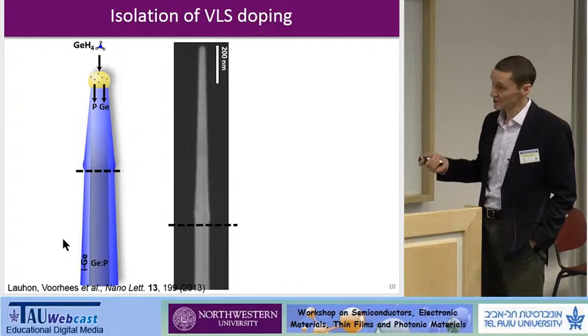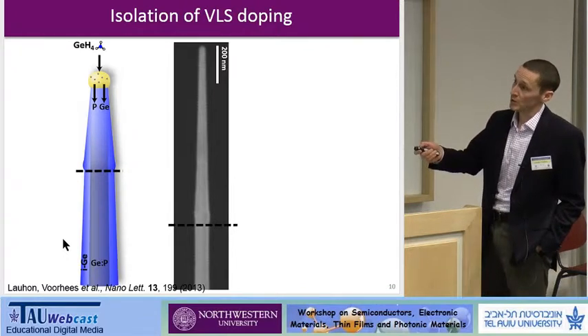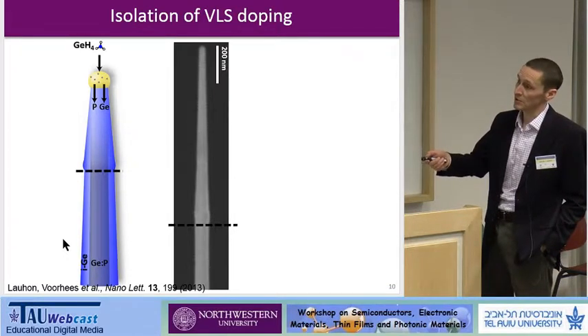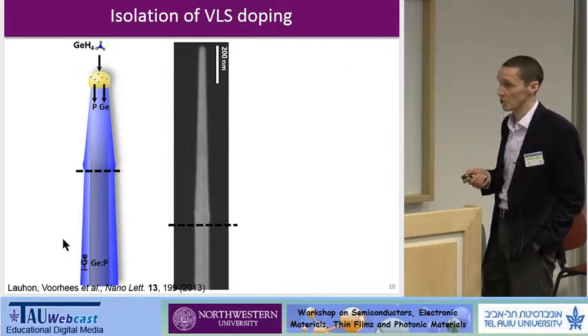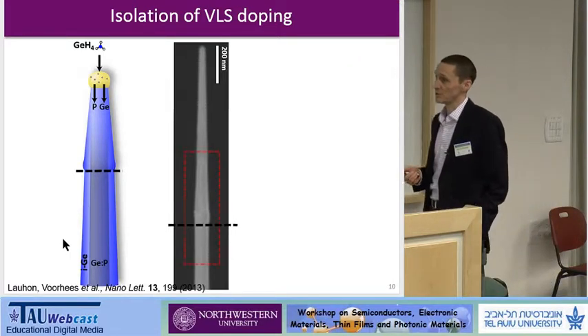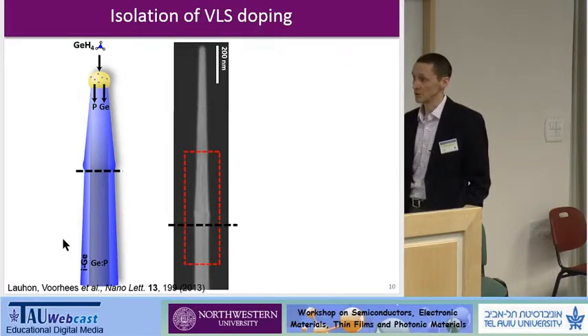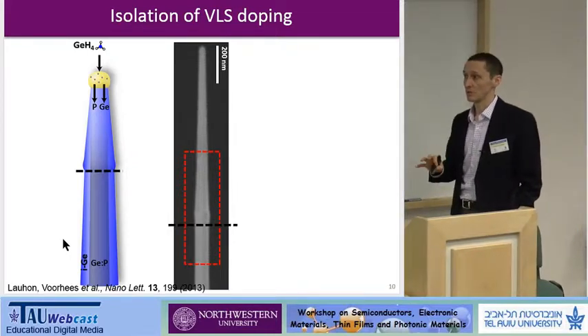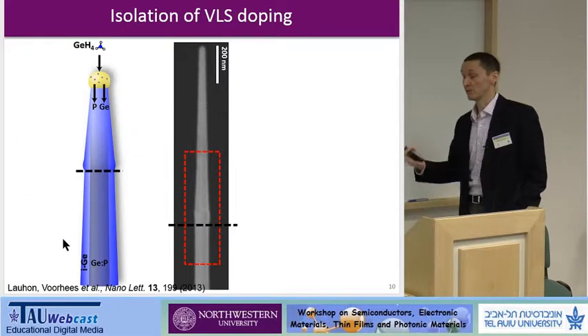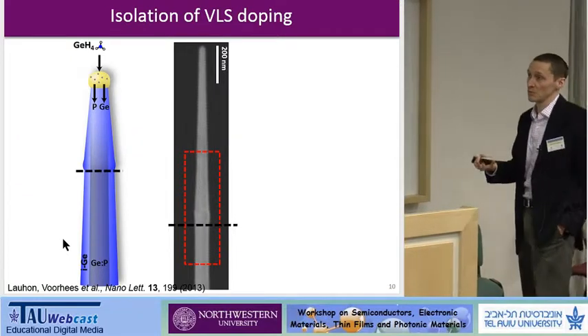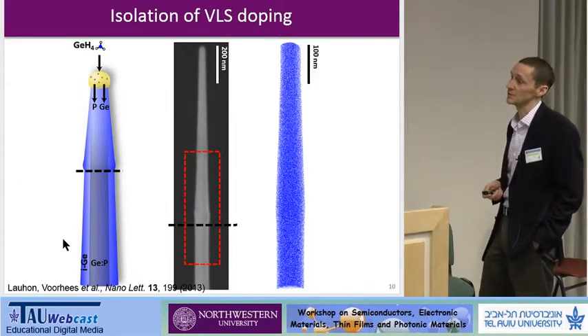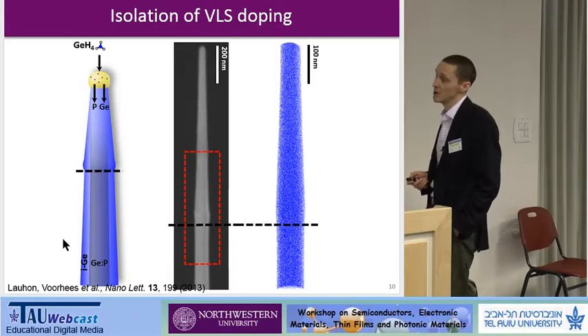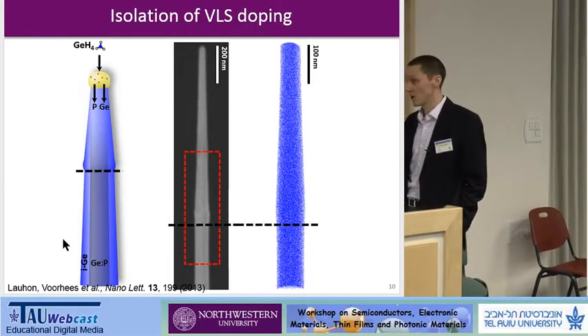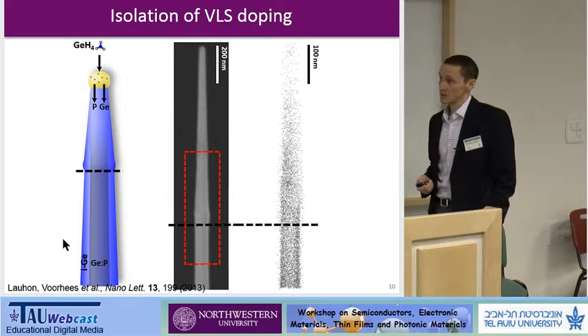This is sort of continuing work in which we tried to isolate further the VLS from the VS doping. And so we're going to look at a part of a nanowire here with atom probe tomography in which this region was grown without any dopant flowing. So the only dopant can really come from whatever's dissolved in the catalyst. Okay, so that's the germanium nanowire. This is the transition where we turn off all the doping. And this is the phosphorus.